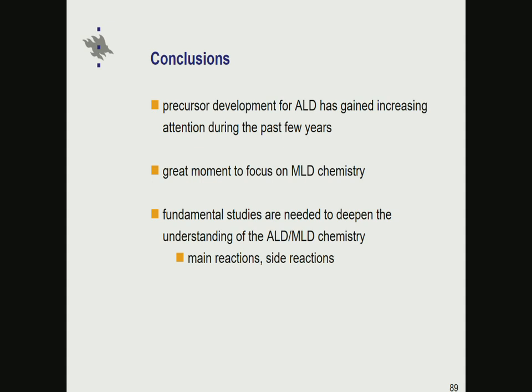Well, I think Christoph was showing the three curves you are expected to show when you are developing ALD chemistry, these saturation curves. They are as a function of time rather than dose, and I think there is a good reason for that. When you are talking about Langmuir, it's pressure times the time of exposure. But in ALD chemistry, our reactions are so fast that at the point when you reach a stable partial pressure with your precursor, you are done already. So when you bring TMA on a surface which is hydroxyl group terminated, everything will react first. And it's very difficult to say what your partial pressure was when you were realizing this saturation. Only once you have saturated the surface is the partial pressure of TMA able to reach a stable level in the chamber.